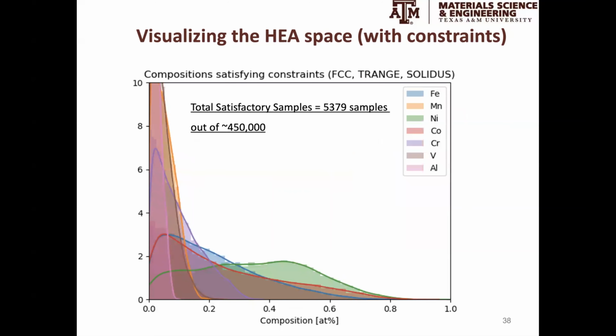If we look at the samples that satisfy all the constraints we set—related to the solidus, the solidification range, and the phase stability of being FCC at 800 Celsius—what we find is this distribution of compositions. If you ignore this axis, it essentially counts the frequency or relative frequency of these alloys.